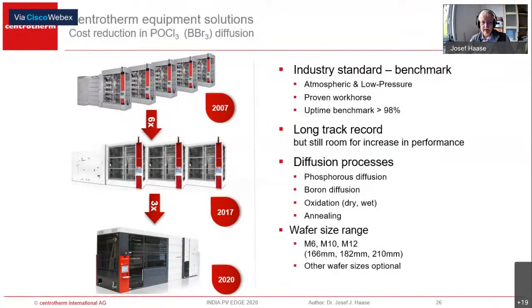Now we move to diffusion. Here you see it's even more severe. From a diffusion furnace 2007 to 2020, we have about an 18 times higher capacity on the machine. It's also the same machine, basic design with an industry standard now available for atmospheric and low pressure processes, proven workhorse, still benchmark for competitors. And the diffusion processes, that are the standard, is phosphorus, boron diffusion, oxidation, and annealing. And wafer size similar to the PCVD M6, M10, and M12, which means 166, 182, and 210 millimeters. Next, please.